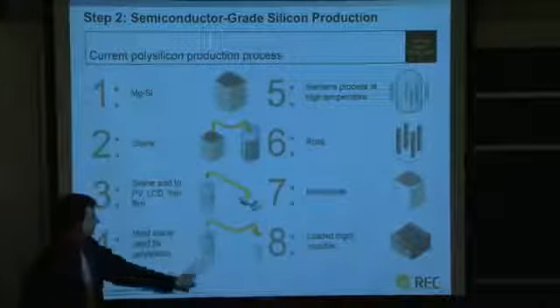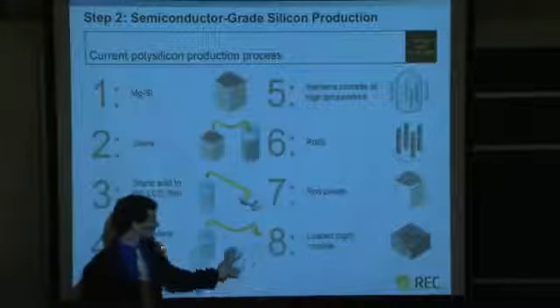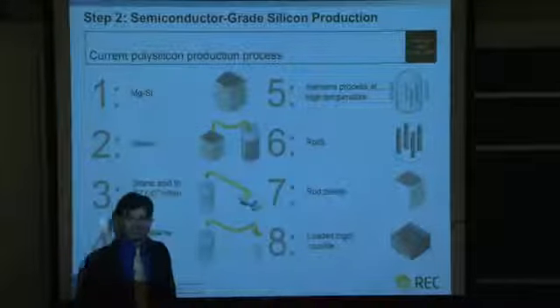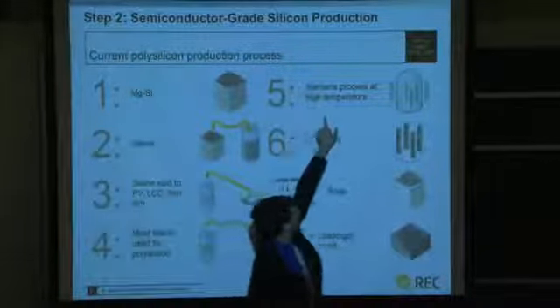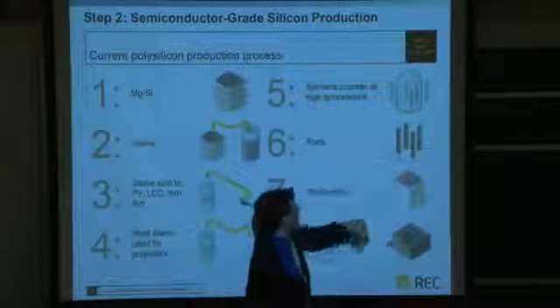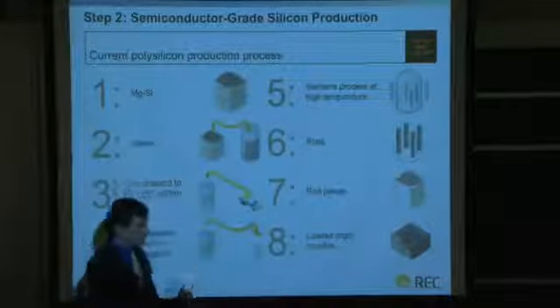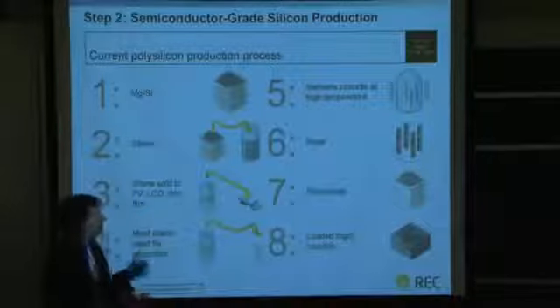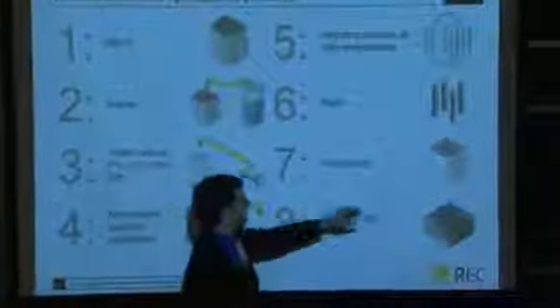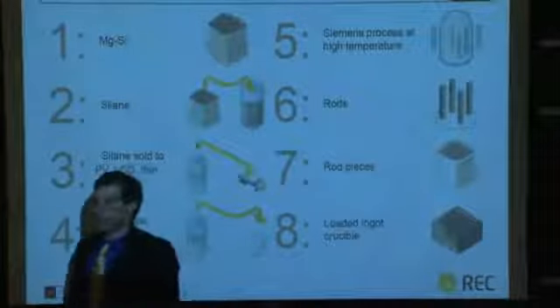Most of the silane is used for polysilicon. The gas has to be converted back into a solid, and that's where this particular process here, the Siemens process, is used. Again, you have a current passing through some seed material, and the gas is being cracked onto that seed. You form these rods. The rods are then cracked into chunks, and then the chunks are loaded into ingot crucibles.